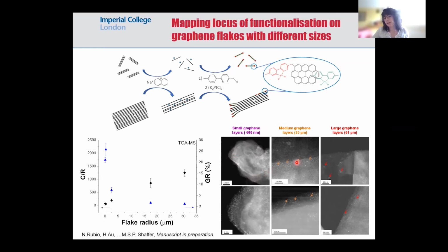And on the other hand, for our medium graphites, we were able to see the platinum more concentrated around the edges. And for larger graphites, they were more concentrated, forming clusters or agglomerates, which fits our theory that the functionalization is initiated by pre-existing defects or also edges. That's why we see them in this case, medium graphites more concentrated around the edge.